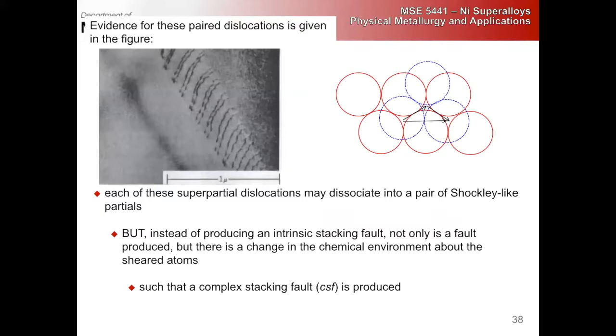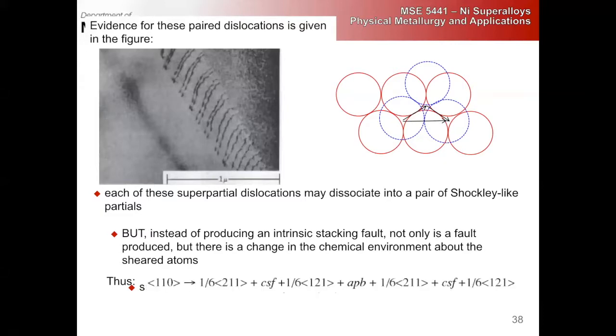But instead of producing an intrinsic stacking fault like it would in the gamma, we have a change in the local chemical environment, so we produce a complex stacking fault. So generally what we have in the gamma prime, right? First we have a Shockley partial from the gamma. It's going to leave behind a complex stacking fault. Another one comes by, leaves behind an antiphase boundary. Another one comes, leaves behind another complex stacking fault. Another one comes and restores us to normal order, right?